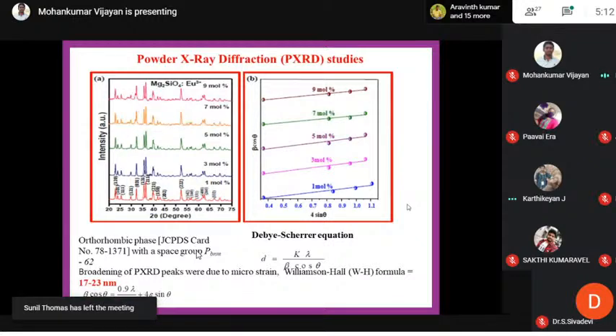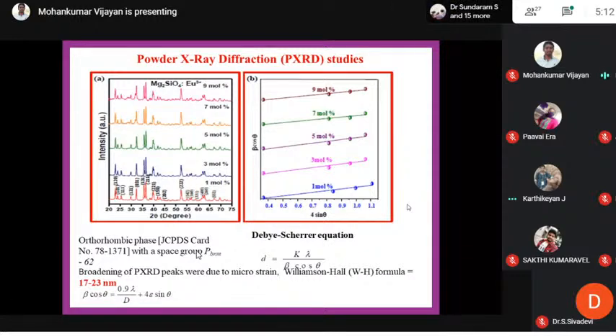It is matching with JCPDS number 78-1371. So the formula which is used for the calculation of crystallite size is D equals K lambda divided by beta cos theta. This is called the Scherrer equation. And also at the right side...